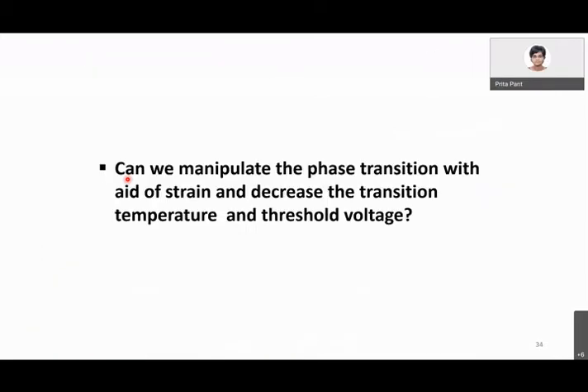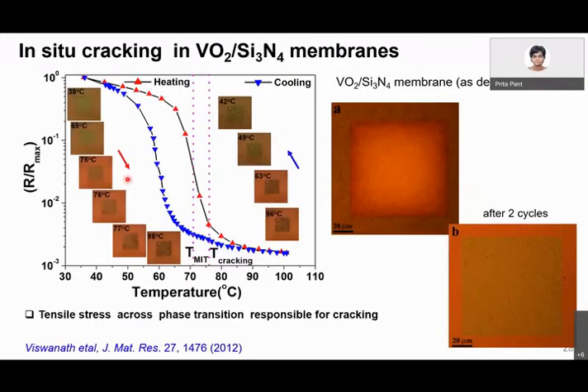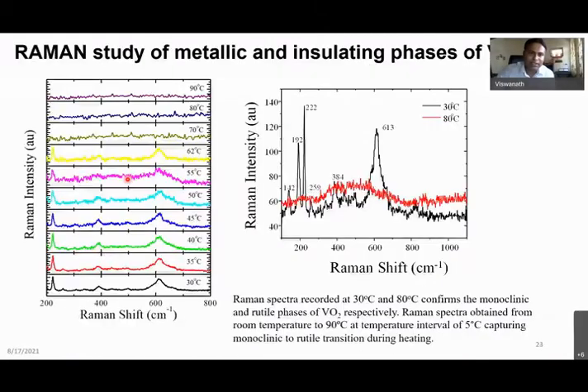So what we could do is go closer to the phase transformation temperature, say around 55 to 60, and then locally indent, and then you see a change in the phase. So there is a trade-off between the temperature requirement and the stress requirement. At room temperature, even with the 6 millinewton, we are not able to find the stress-induced phase transformation in VO2.